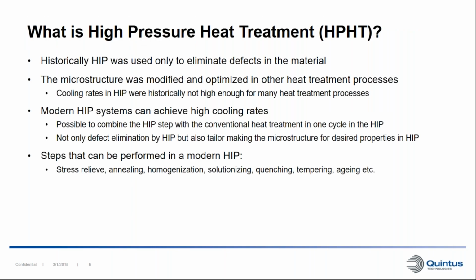So what is high pressure heat treatment? Historically, HIP has been used to eliminate defects in the material only. To optimize or modify your microstructure was normally performed in other heat treatment processes. And the reason for this was that back in the day, the HIP system had a relatively slow cooling rate, so they weren't really high enough to perform many of the heat treatments. However, today we can achieve very high cooling rates in a modern HIP system.